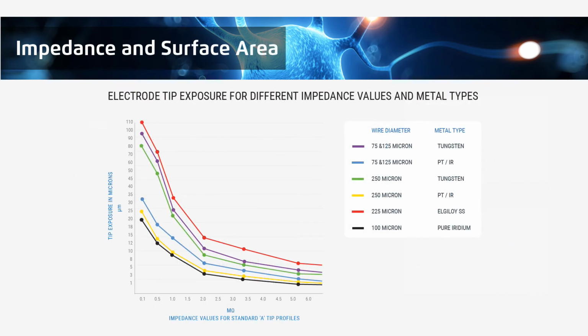Many researchers commonly ask, what's the relationship between impedance and surface area for the electrode that they're using? This, of course, varies depending on what metal you have selected for your electrode, as each metal has a different concomitant impedance, as I mentioned earlier. And this chart really illustrates that point, where you can see the pure iridium electrode at the very bottom, the black line, tends to offer much lower impedances at the same surface area as the other metals that you see, with the highest being Elgiloy, the red line at the top, which has much higher impedances for the same surface area.